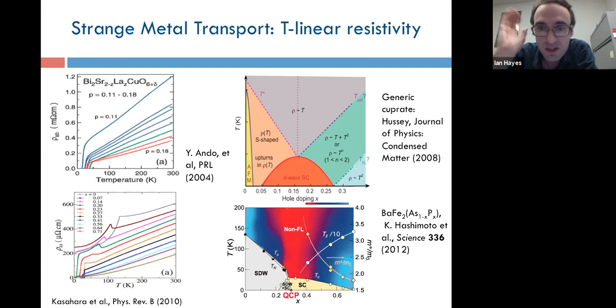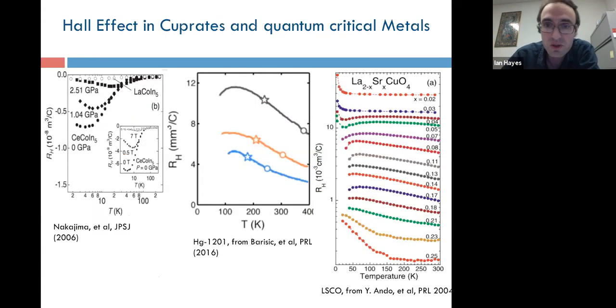For my purposes, I just care that the T-linear resistivity is this thing that is correlated with optimal Tc in lots of cuprates and now lots of nickelates. So the T-linear resistivity is a famous piece of this, but there's also behavior in the Hall coefficient that is common to all these systems.